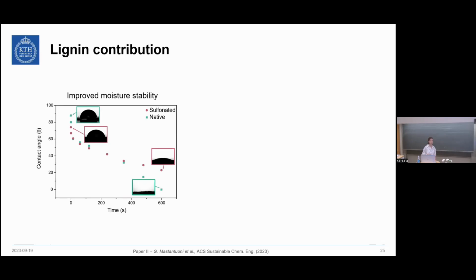Furthermore, as we are preserving the lignin, then we could also see some additional properties. First of which is improved moisture stability. So if we look at the sulfonated densified sample, so the pink line, then we can see that a drop that is deposited on the surface actually can stay stable up to more than 10 minutes. Instead, if we do the same thing with the native densified wood, then the drops disappear completely.